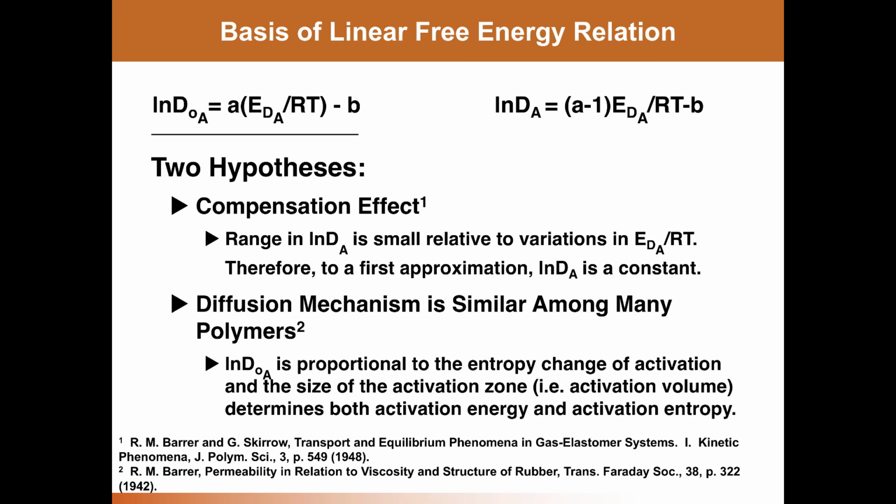If there were some uncertainty in the experimental diffusion coefficients that tilted that line among the data points just a little bit up, for example, that would tend to give it a steeper activation or larger activation energy of diffusion, making the line steeper, and that would also give it a higher value of D0. If, on the other hand, there was uncertainty in the data that tended to tilt that line a little bit down, it would make the apparent activation energy of diffusion lower, and it would reduce the value of D0.